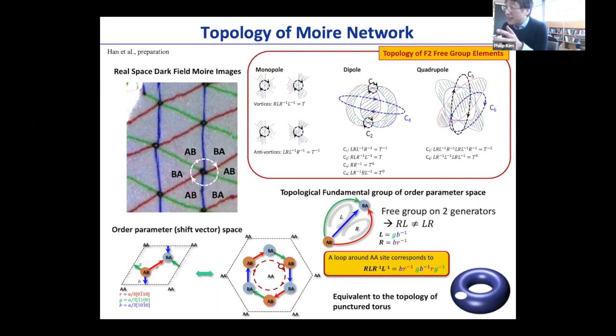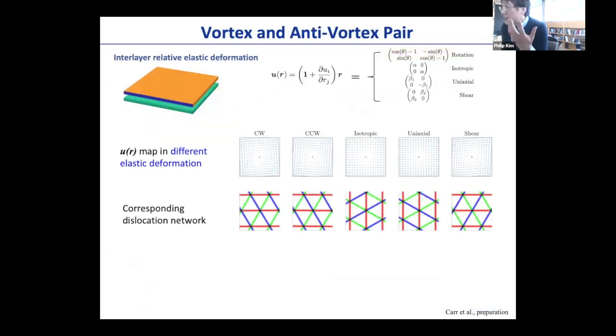And moreover, not only twisting, there's a way that you can create this type of general Moire lattice even further. You can create a vortex and anti-vortex array by twisting or shearing, and then isotropic expansions or uniaxial expansions, and all of this creates different types of Moire patterns, or in equivalent language, networks of these dislocations of different kinds, and they tend to show very different structural properties and potentially the associated electronic properties.